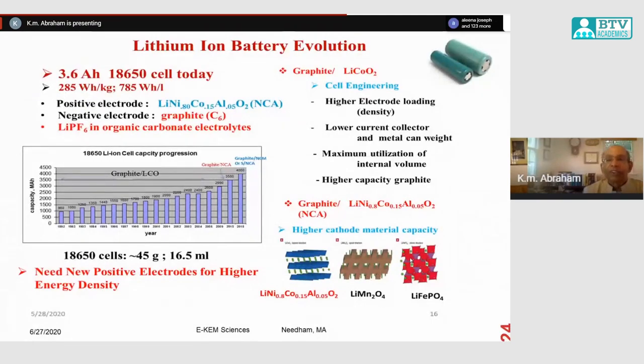All right. So this is the lithium-ion battery evolution. In 1992, when Sony came out with it, this 18650 cell had about 1 ampere hour capacity. It gradually increased, and by 2004 or 2005, with the same electrodes, they were able to more than double the capacity of the battery through electrode loading and cell engineering. Basically, most of the early improvement came from cell engineering.